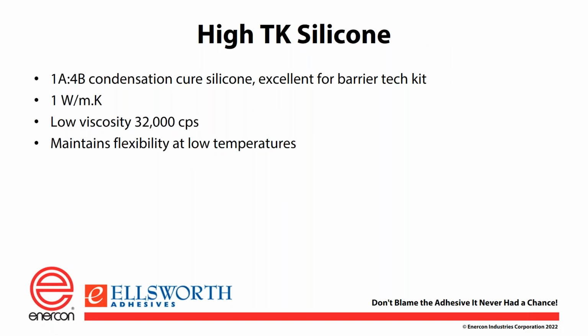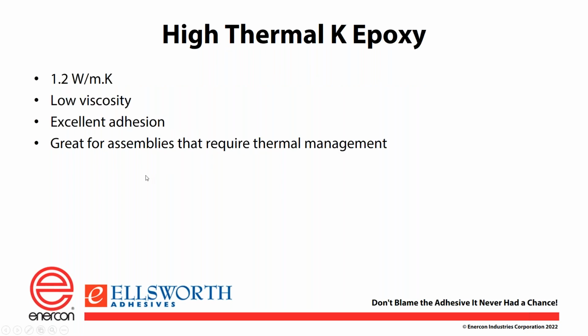High thermal conductivity silicones, in excess of 1 watt per meter K with low viscosity, usually would be of value in applications associated with battery packaging along those lines, but a very good thermally conductive material. And I think the next slide is the high thermal K epoxy. Similar, in excess of 1 watt per meter K, low viscosity. This particular product has very high adhesion to, I think it was a nickel aluminum substrate that was used. And it is also available in side-by-side cartridges. So there's some advantages with that one as well.